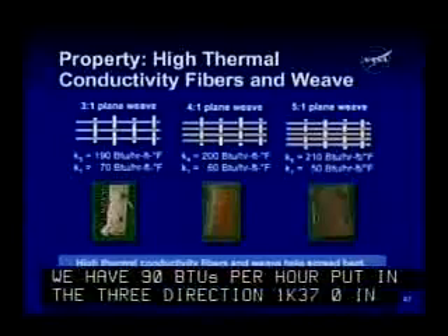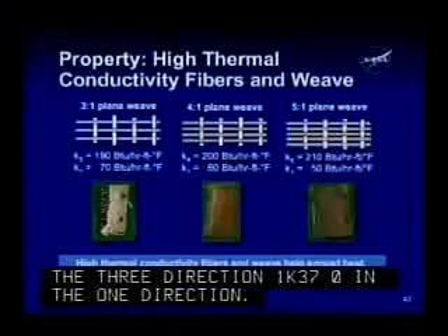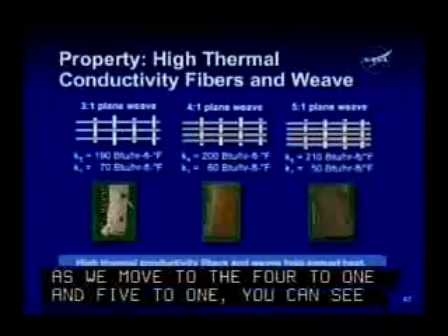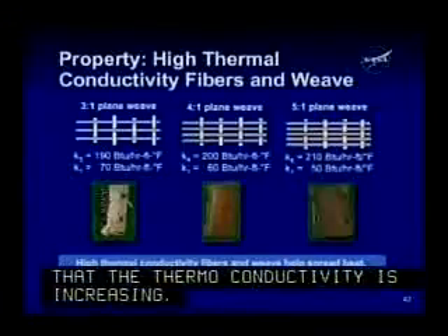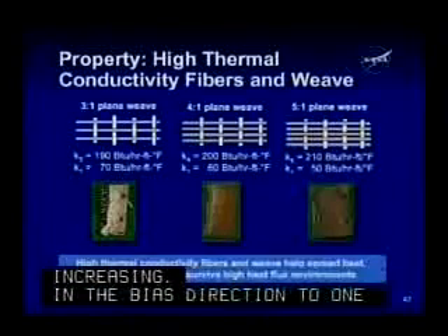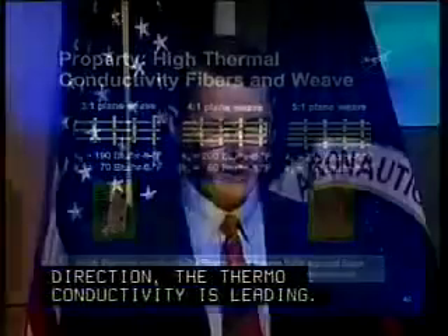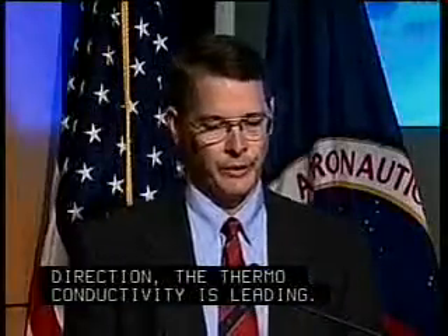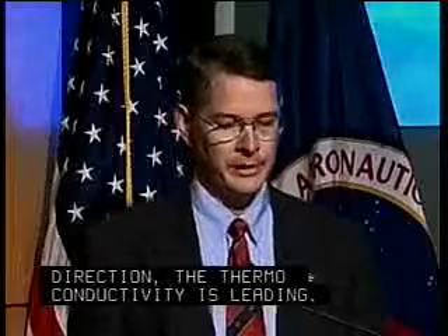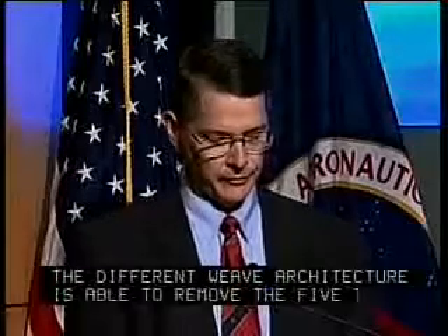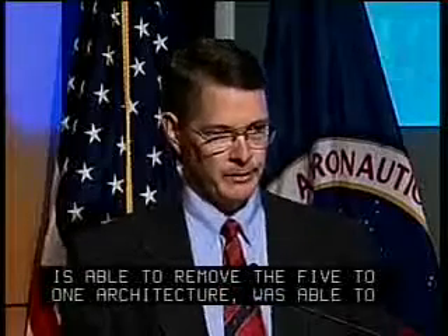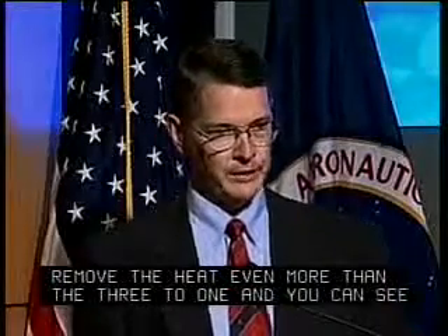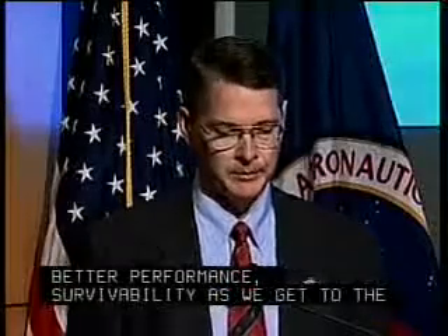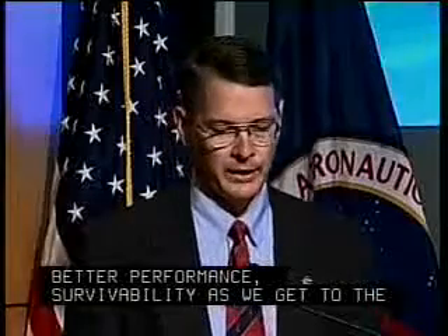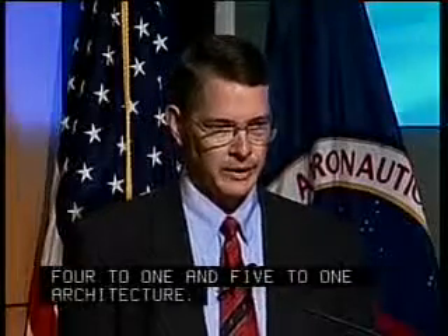For the 3-to-1, we have 190 BTU per hour foot F in the 3 direction and 70 in the 1 direction. And as we move to the 4-to-1, 5-to-1, you can see that the thermal conductivity is increasing. In the biased direction, the 1 direction, the thermal conductivity is decreasing. Photographs show leading edges with the 3-to-1, 4-to-1, and 5-to-1 architecture that were arc-jet tested. The 5-to-1 architecture was able to remove the heat even more than the 3-to-1, and you can see better performance, survivability as we get to the 4-to-1 and 5-to-1 architecture. Next chart, please.